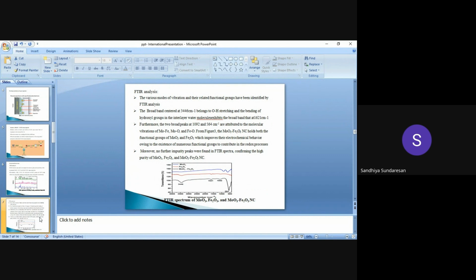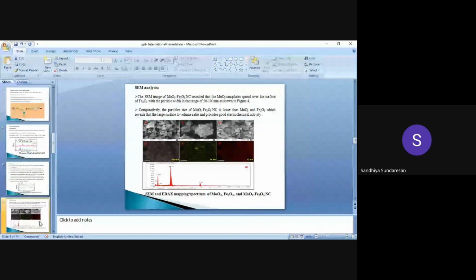And furthermore, the two peaks at 1092 and 564 cm^-1 are attributed to the molecular vibrations of molybdenum-oxygen and iron-oxygen bonds. This is figure 3. Moreover, no impurity peaks were found in the FTIR spectra, confirming the high purity of molybdenum dioxide, iron oxide, and these composites. And these are the SEM images of molybdenum dioxide, iron oxide, and its composites.